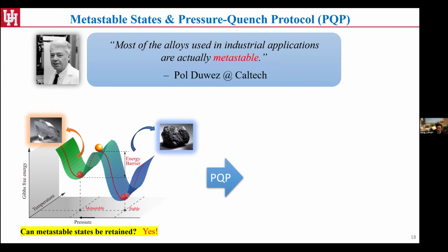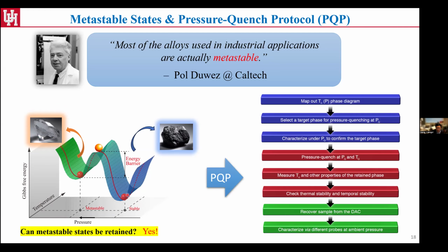Based on this, we created this pressure quench protocol, and it consists of 3 stages. I use colors to distinguish them. The first stage is really nothing new. That's really the traditional high pressure study. You apply pressure, you map out the properties as a function of pressure, step by step. Based on that, we can choose a targeted phase. Speaking for Tc, we're really just trying to focus on the maximum Tc on the Tc-P phase diagram. Once we find that critical pressure, which we later call the quenching pressure, we move on to the pressure quench stage, which is in the red color. So we do the pressure quench.